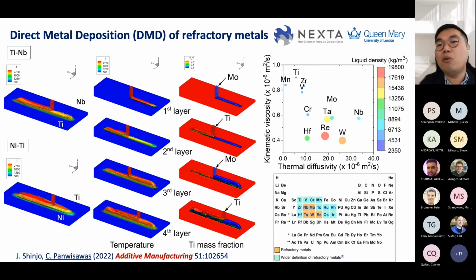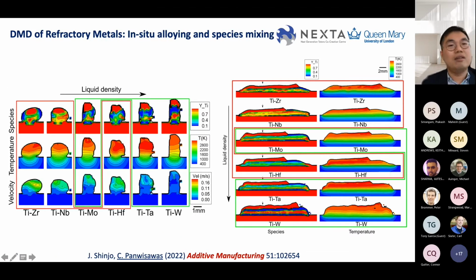Why it doesn't work from a thermal chemical fluid point of view? We can have some explanation on that. That's because, for example, we are looking at the same map, viscosity versus diffusivity, but we now focus on the refractory metal. We can see from the next slide that there's some trend that some heavy liquid density doesn't mix very well at this process condition. You will see tungsten make it nearly a laminated structure compared with titanium niobium or titanium zirconium. And this is why some of the application using tungsten additives doesn't mix very well. But anyway, we can use this kind of simulation to explore even further. How can we improve this mixing?